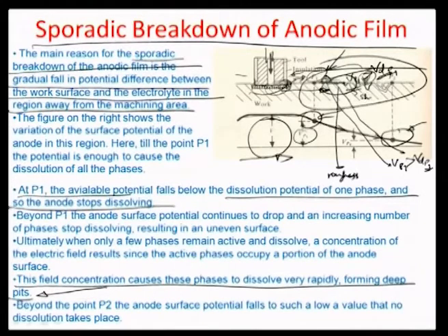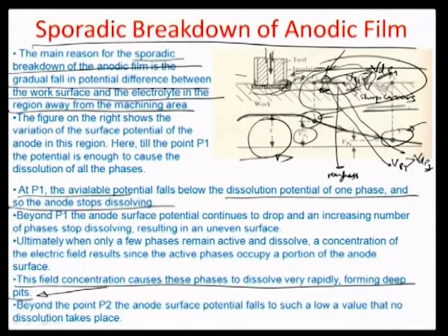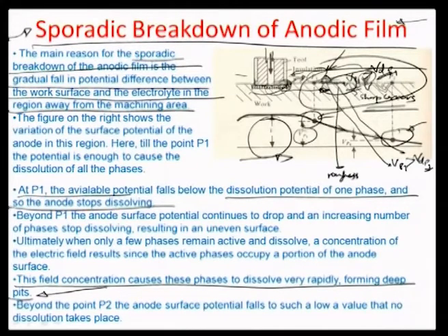The field concentration causes phases to dissolve very rapidly because of selective dissolution and the formation of sharp corners. This is certainly highly undesirable for an ECM process and can be one of the main mechanisms for introducing surface roughness, even though ECM is supposed to be a self-leveling and smooth operation.